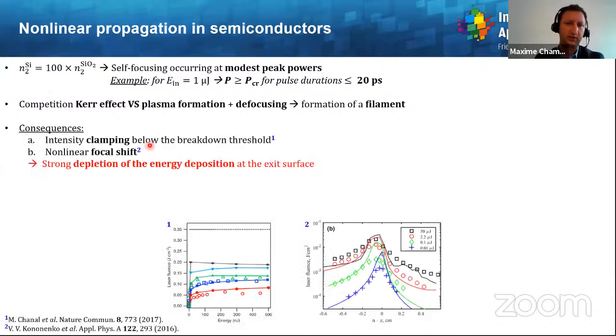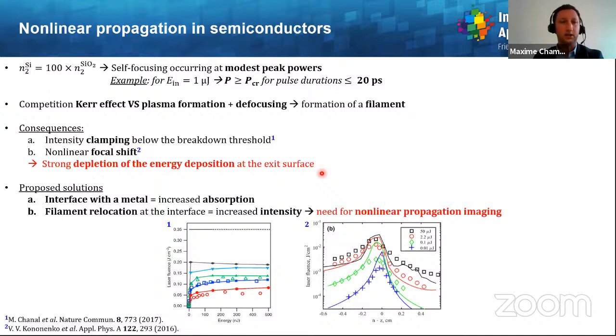Then the two consequences, I already talked about this. And again, there is a strong depletion of the energy deposition at the exit surface of silicon, so actually the interface between silicon and copper in our case. So the solutions we propose are, first, we use an interface with a metal, meaning that the absorption will be drastically increased, which is pretty good. And second, we propose a filament relocation method to get an increased intensity at the interface between silicon and copper.